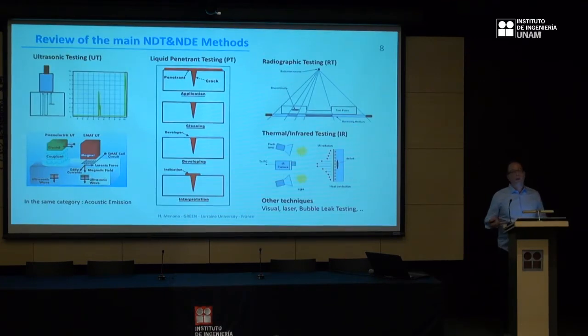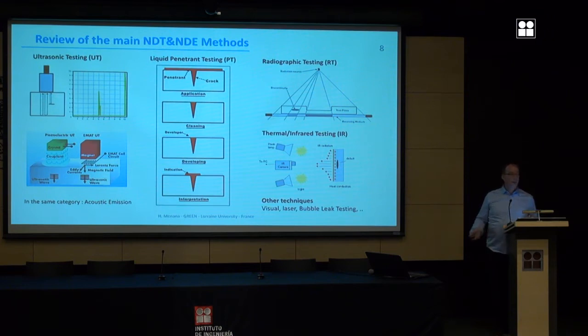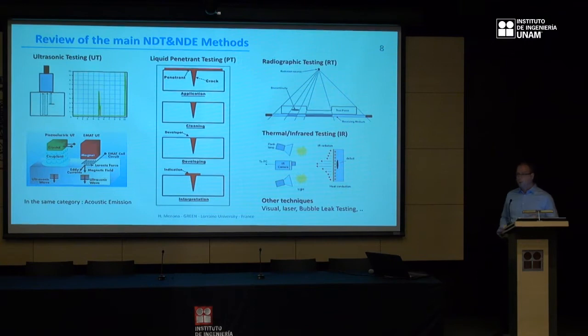Several methods are used to characterize materials. The most common one is ultrasonic testing, given in this figure. It's an ecography. We realize an ecography of the tested material. It's a pulse echo method. We create ultrasonic waves in the material, and we use the different echoes to characterize thicknesses, velocities of acoustic waves, or even eventually a defect or a flaw. We use the time of flight of the acoustic waves as well as the magnitude of the echo we receive.